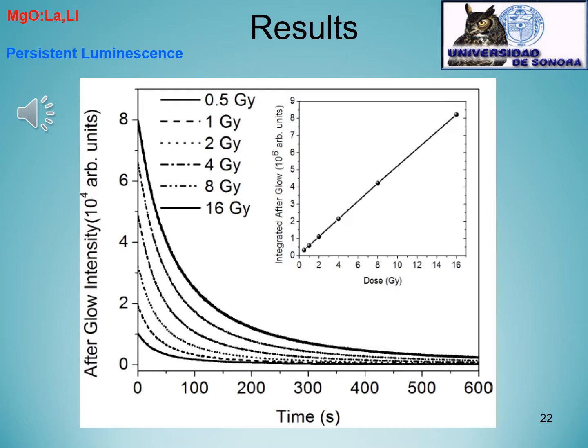In this case, we measured the afterglow intensity as the dose was increased. We can observe that the afterglow intensity increases, and the inset graph shows the linear trend from the integrated afterglow, which is the area beneath each decay curve for different doses for this afterglow property.